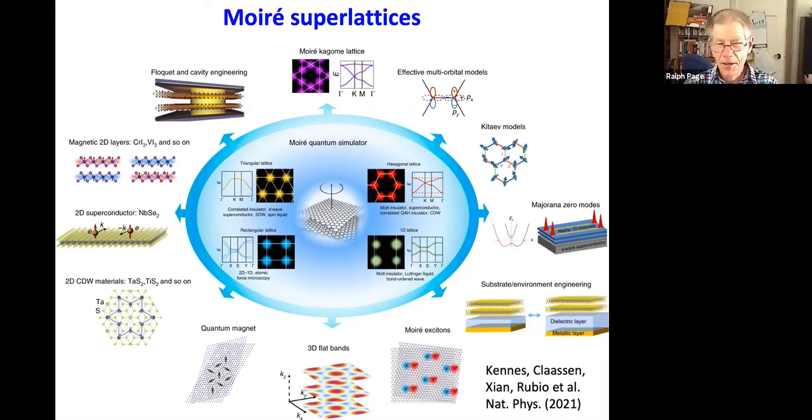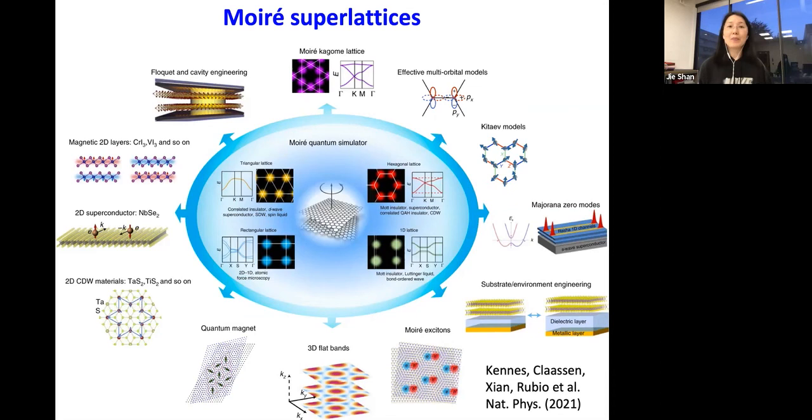Okay. So we first determine the capacitance of those gates. So we know exactly that if you apply a certain voltage, you get into a certain doping range. That can be done very accurately. So the question is the spread in terms of doping density. The gate control is very, very accurate. There are some defects, for example, and we estimated that to be one to two orders of magnitude lower than the half filling density. So the spread is very, very small. Thank you.